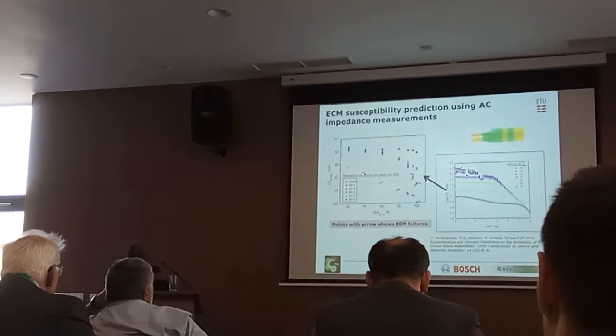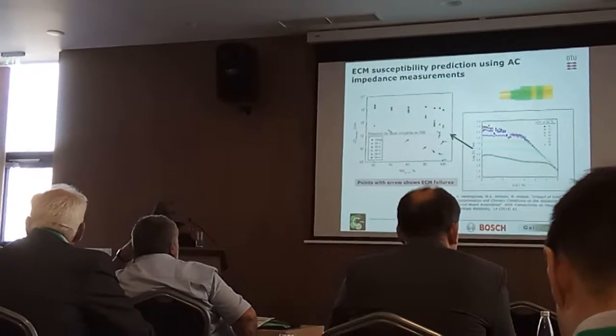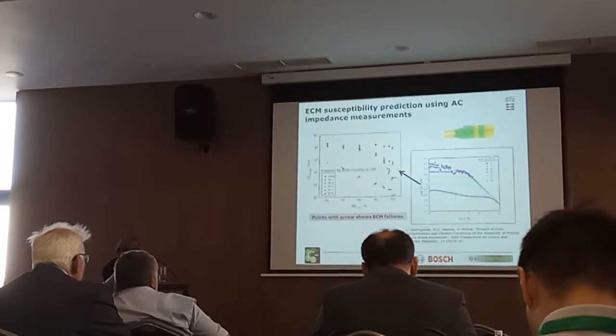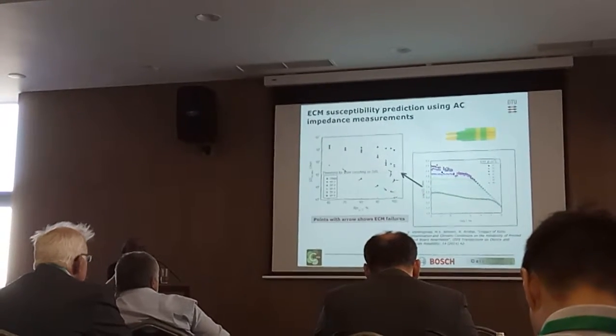When it comes to that, you can see the correlation — the impedance related to different levels of humidity when circuit boards are exposed. You can see that at different humidity levels the impedance curve changes, and if you do an electrochemical measurement, you get electrochemical migration at different humidity levels. So you can see a very good correlation between the impedance curve as well as the electrochemical measurement — where the water layer thickness goes beyond a level, those are the points where you start seeing electrochemical migration. The impedance measurement can be performed in our lab, and we can also correlate it with DC measurement.